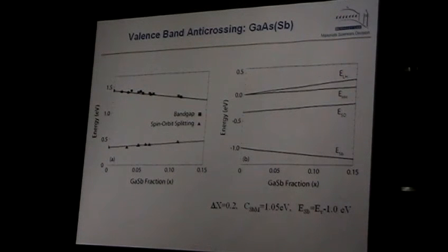And in this calculation, in our estimate, there are basically two parameters. One is you have to find where is your antimony level, or nitrogen level, or whatever you start adding. So this is the position of the level, and in this case it's valence band edge minus 1 electron volt. So this is located at this point. The only other parameter is the coupling parameter between the extended states of the gallium arsenide matrix and this antimony state. This coupling parameter is much smaller. It's 1 electron volt. In the other materials like gallium arsenide nitride, it was almost 3 electron volts. So this is the set of parameters.